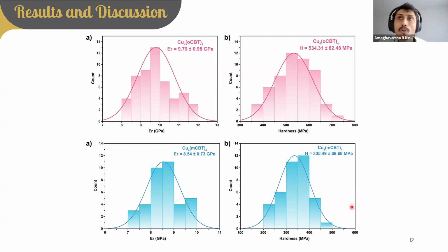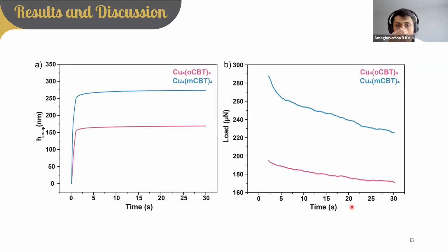Then we went on to study the time-dependent mechanical properties in these crystals. As I mentioned earlier, whenever we indent the sample, we give a little time for loading, holding, and unloading. But in time-dependent measurements, we indent the sample in 1 second. That is what is shown here in this sudden increase in the displacement. Then we hold the tip inside the sample for 30 seconds to observe the changes in load or displacement.